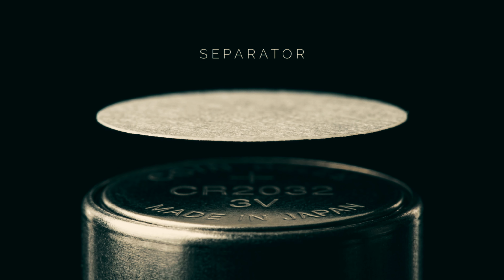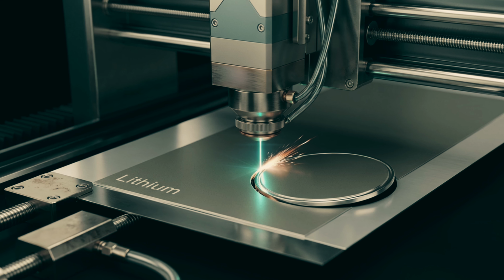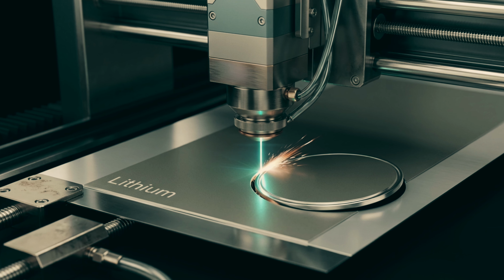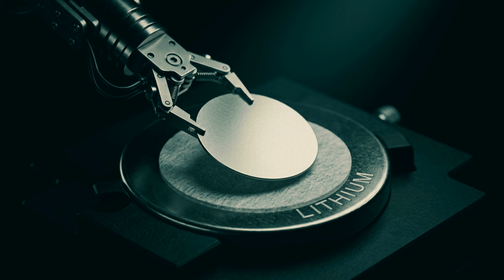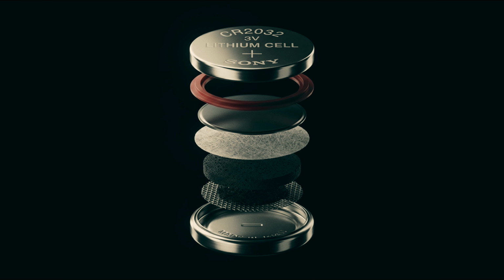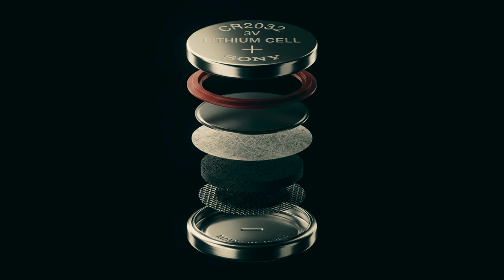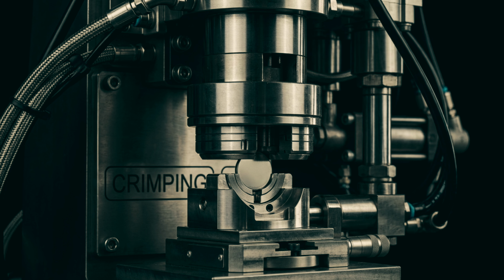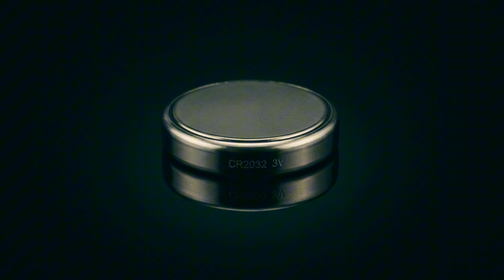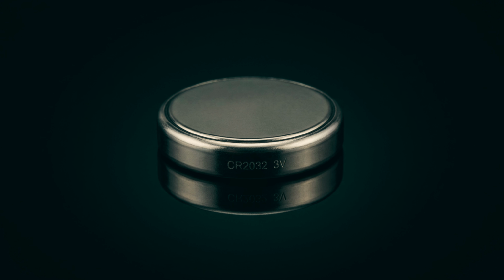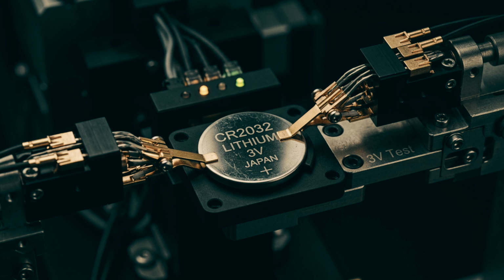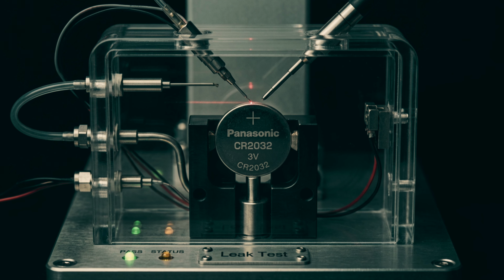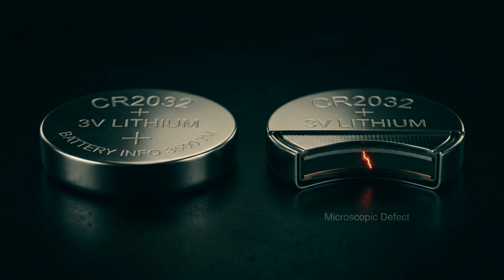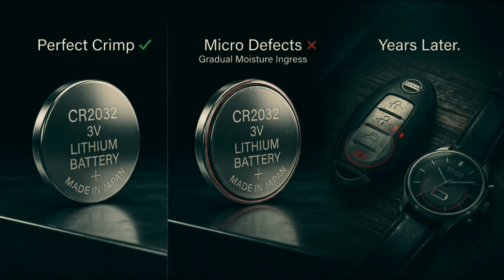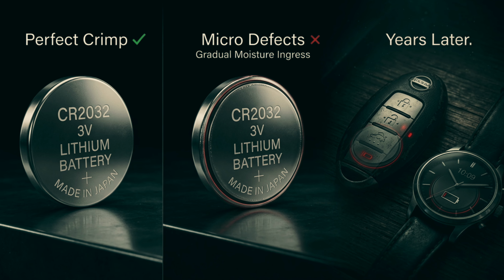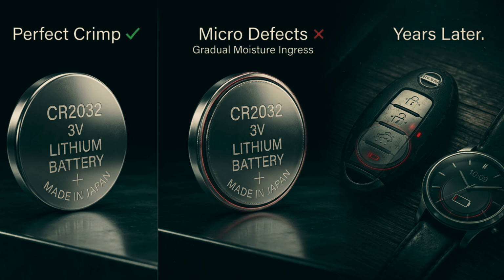A paper-thin separator is added, followed by a lithium foil disc cut to an exact diameter, often with tolerances measured in fractions of a millimeter. The two halves of the casing are crimped together under precise force. Too loose, and the battery leaks. Too tight, and it can crack the internal components and ruin the cell entirely. Each finished coin cell is voltage tested and leak tested individually, since even a tiny defect can't be caught visually at this scale, and a single bad crimp can go unnoticed until the battery fails years later inside a device.